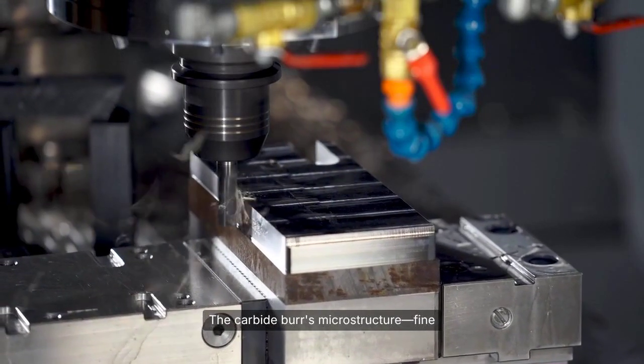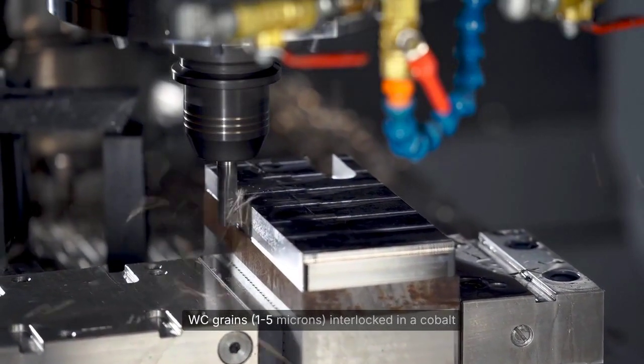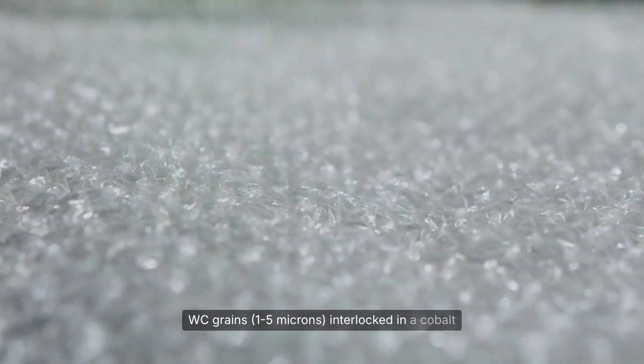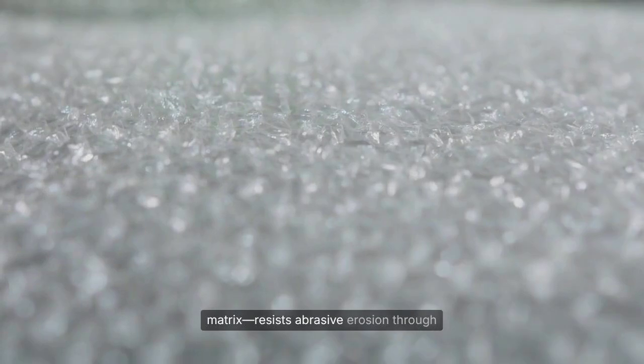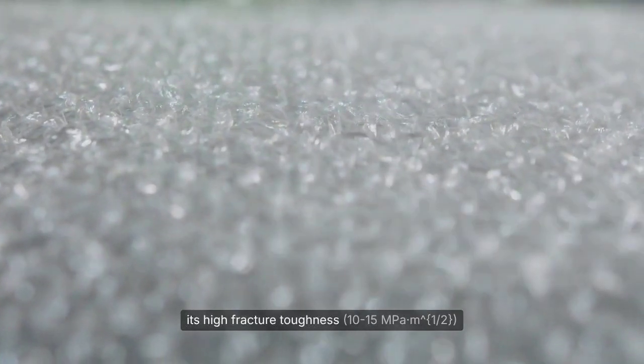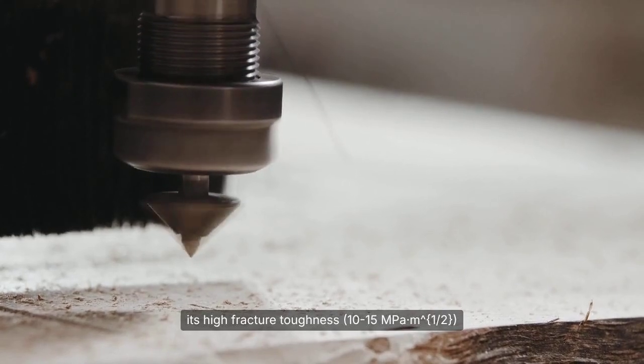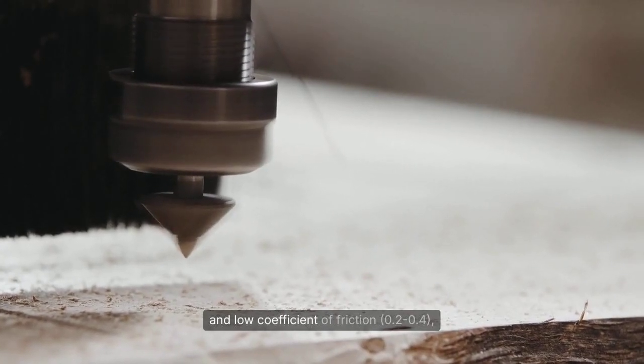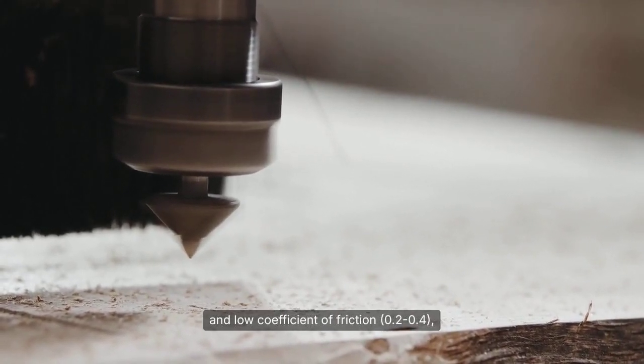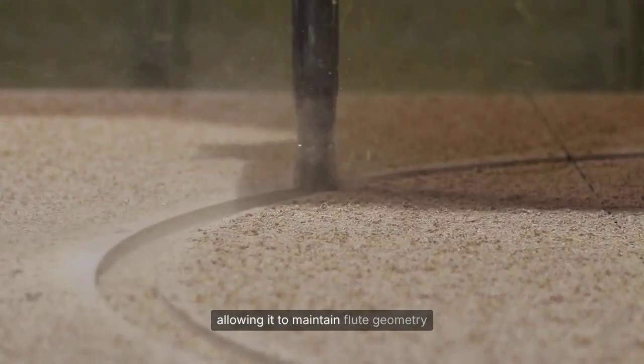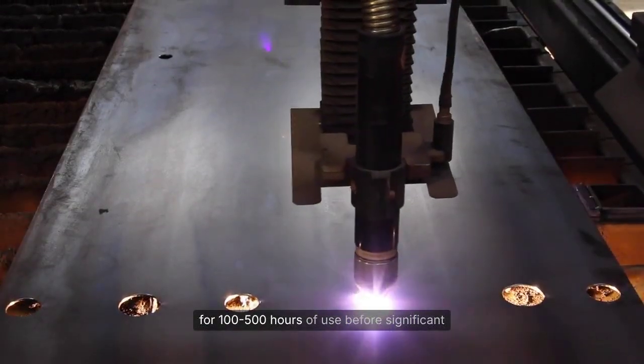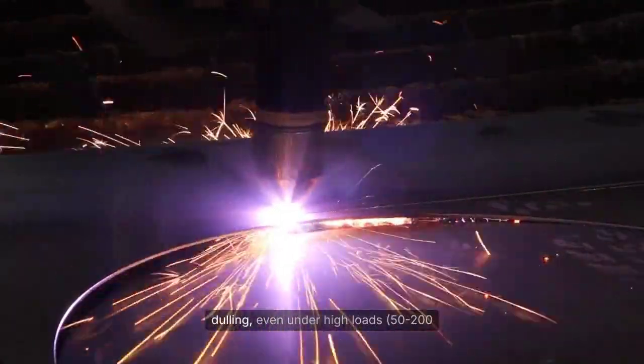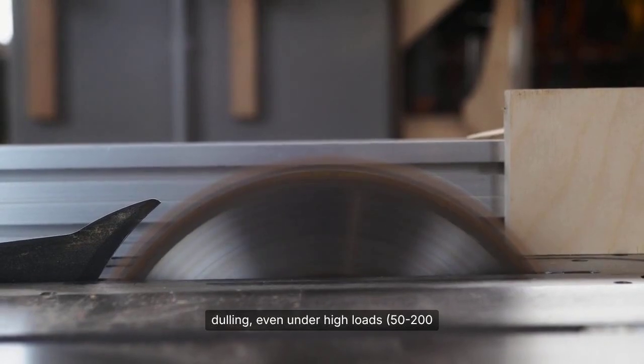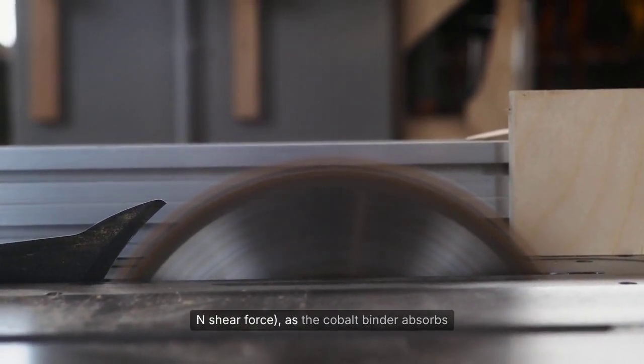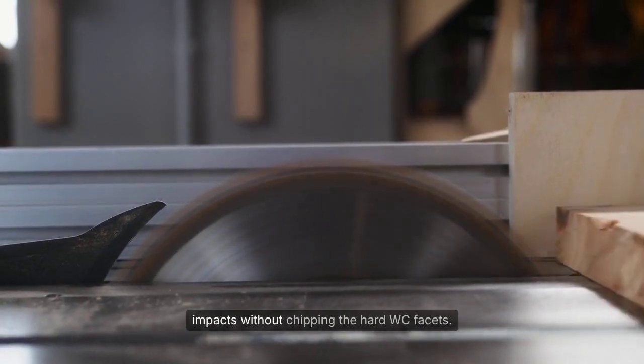The carbide burr's microstructure, fine WC grains, 1 to 5 microns, interlocked in a cobalt matrix, resists abrasive erosion through its high fracture toughness, 10 to 15 megapascals per square root of meter, and low coefficient of friction, 0.2 to 0.4, allowing it to maintain flute geometry for 100 to 500 hours of use before significant dulling, even under high loads, 50 to 200 Newton shear force, as the cobalt binder absorbs impacts without chipping the hard WC facets.